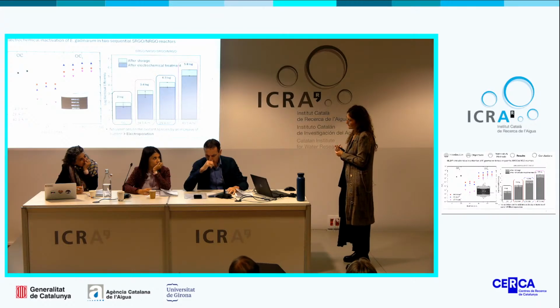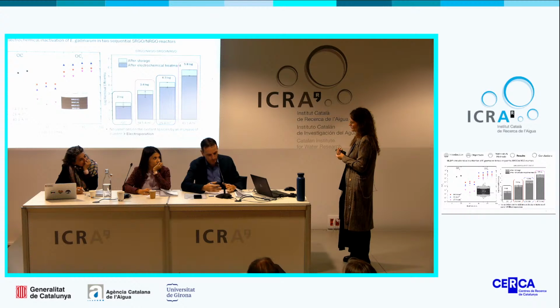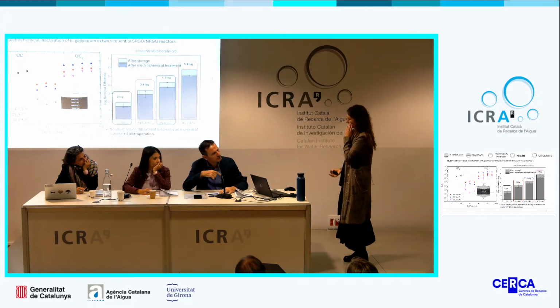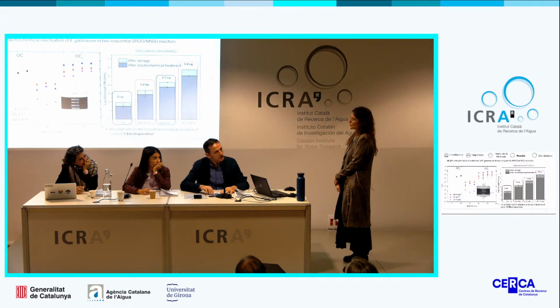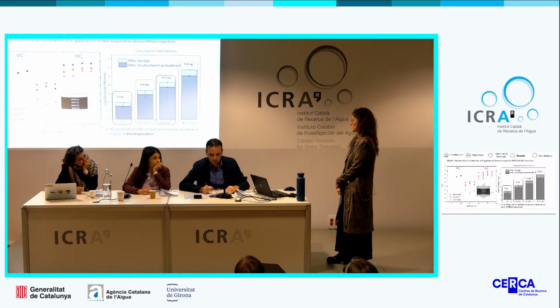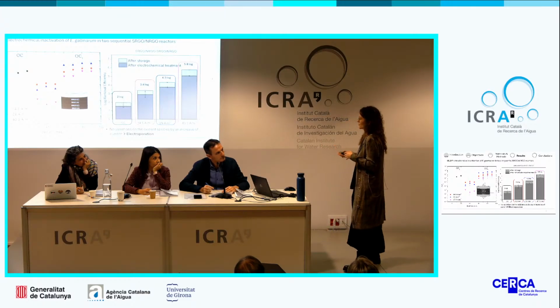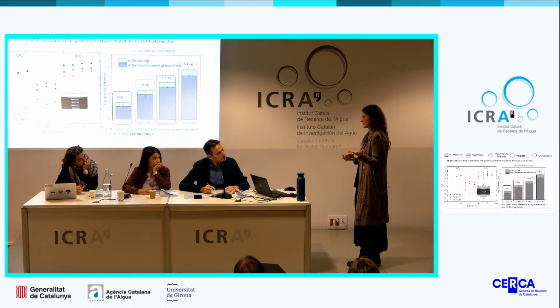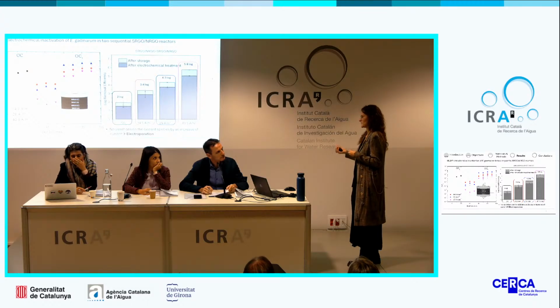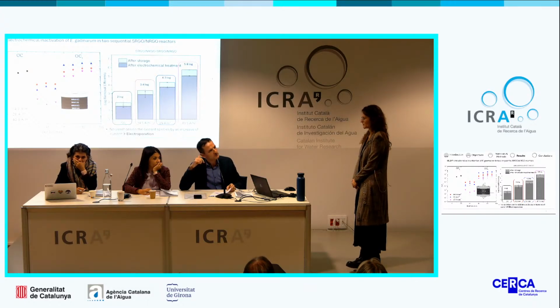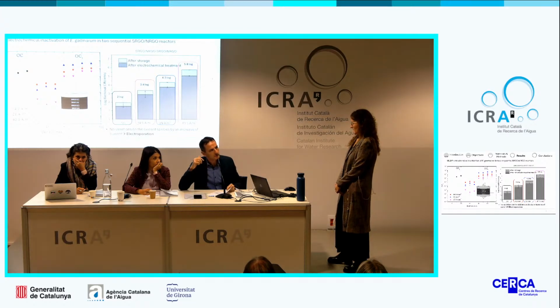You mentioned several times that one of the advantages is that you don't produce chlorinated byproducts. And you attribute this to the lack of electrocatalytic activity of these anodes toward chloride oxidation, right? Yes. But ozone cannot oxidize chloride and produce these chlorinated species? Ozone, yes, in higher doses, but we are not producing those higher doses. Okay. This is one of the limitations of, for example, ozonation treatment, which in some cases, depending on the matrix, needs a really high dose, and that can favor the formation of chlorinated byproducts. But have you measured any chlorine? I mean, have you experimentally measured? Yes, some, yes, we did, but we didn't report it.